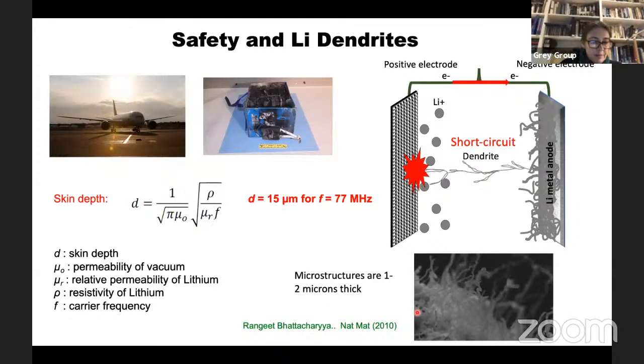I want to talk now about some of the work we've done on safety and dendrites. In the days when we could all take more planes, the Dreamliner was introduced by Boeing a few years ago, and it ended up being grounded for at least a year because they had problems with the lithium-ion battery. The thought was that this was due to lithium dendrites. You can't actually use lithium metal, you use graphite instead. The reason for that is as you cycle backwards and forwards, you form these mossy structures on the surface, and they can eventually become dendritic. You get short circuits, you get heat, and that's what causes some of these fires that I've shown you.